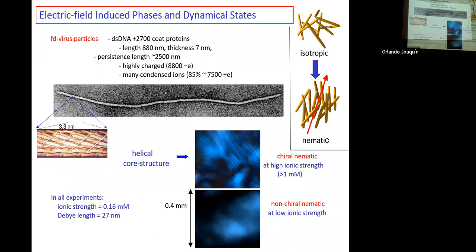Now, as these rods are close together, they feel this twist, because of the chiral structure, this screw-like structure of the surface. So they make a twist, and you get the so-called cholesteric state - this vector will propagate like this. And that's why it's optically polarized - if you look at the solution, you will see this.